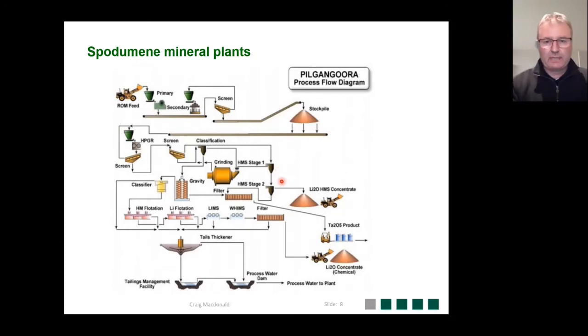So in this particular case, what's happening is the floats, or the cyclone overflow, is recovered, and that's producing the DMS concentrate. The sinks in this particular case is recovering a tantalite concentrate. What happens is the rejects from DMS and the fines is actually ground in a grinding mill. From the grinding mill circuit, we tap off a -1 millimeter product, which is fed through spirals. The concentrate from the spirals is producing a tantalite concentrate.